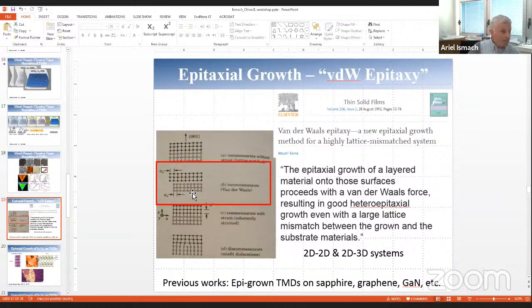However, in van der Waals layers, in 2D materials, because there is no covalent bonding, just van der Waals, you can in principle grow van der Waals epitaxial growth, even though there is no commensurism. Therefore, you can grow layers where the mismatch with the substrate is much larger than allowed in commensurate epitaxial growth. The term van der Waals epitaxy was coined by Koma about 30 years ago. Since then, many 2D materials on 2D materials or on 3D systems were shown to be growing.